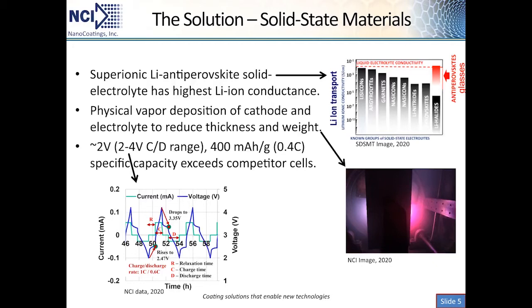these layers. In the middle figure shown on the right, you can see the two different colored plasmas. On the other side of a specimen holder plate, we have a foil on the other side of that. We're doing co-deposition of cathode and electrolyte material and then finishing with pure electrolyte.